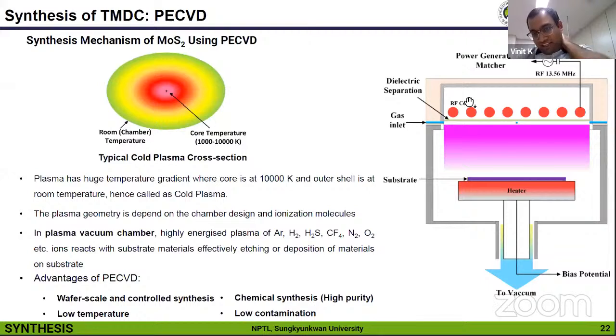So on the right hand side, there is the schematic of our plasma CVD. As explained earlier, there is a typical heater arrangement. On that, our substrate is placed, and then we put this chamber under vacuum, and then we introduce the gases, mainly argon and H2S in this case, or there are different combinations of gases we can use, such as H2S, CF4, N2, O2, depending on the material we want. From these gases, we can make plasma using this RF coil, which is also called a radio frequency coil. From this, we can generate the plasma and synthesize our material.